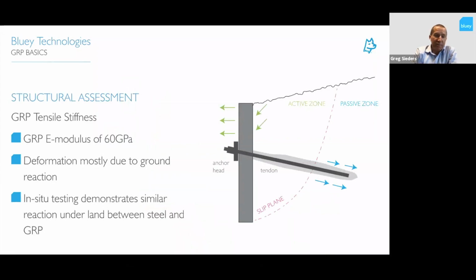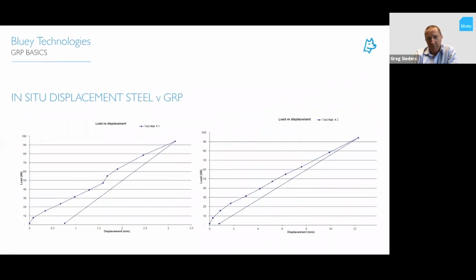And that's where we talked about the modulus of the GRP. Being a more flexible bar, if you do have it going up to higher loads, you'll see more deformation in your GRP bar, and you'll see cracking in your shotcrete facing and the likes. But most of your deformation generally occurs at your grout soil interface. We've done extensive in-situ testing between a GRP and steel bar side by side to justify this and show designers and authorities this is where the deformation is happening. And that's what we'll cover off to show you here.